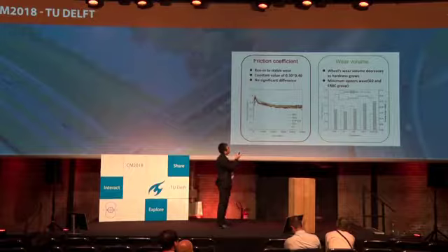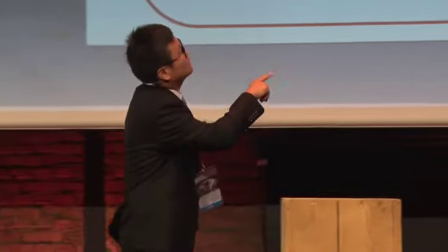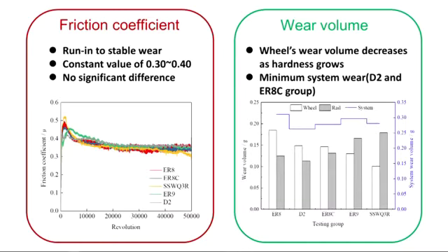And on the right is the wear volume of our tested specimens. As you can see, the wheel's wear volume decreases as the wheel specimen's hardness grows. Yes, in the black, yes, the black one. And up in the figure, we can see a black line and a blue line. This is the system wear of our specimen group. And we have the lowest system wear in the group of D2 and ER8C.